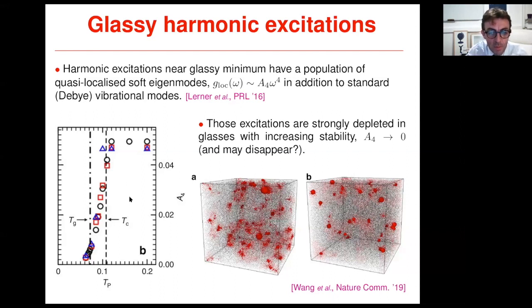But there is a new population of quasi-localized harmonic excitations, which is described by this density of states, which increases as the fourth power of the frequency. So the Debye density of states for crystals would increase as omega to the d-1. So it's different from the Debye plane waves. It was also shown using these tools that I introduced, this swap Monte Carlo algorithm, that if we follow the evolution of this